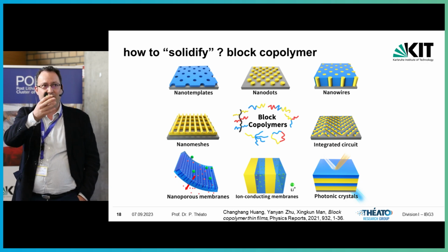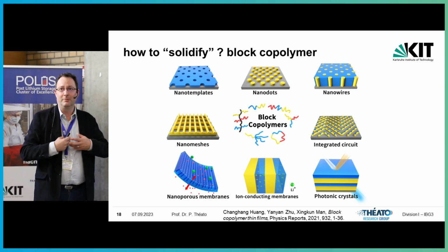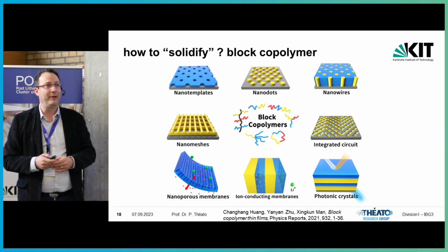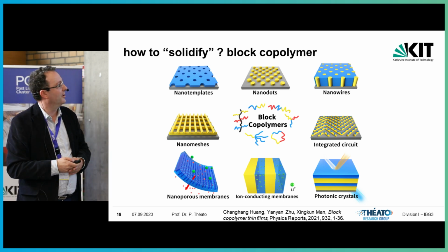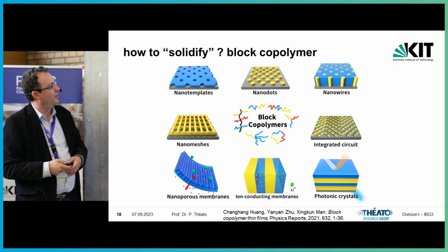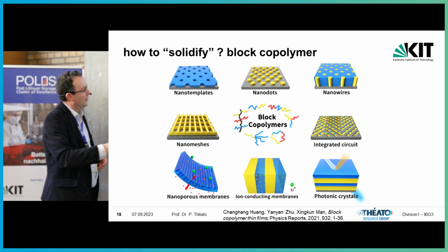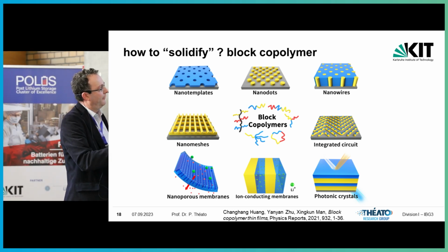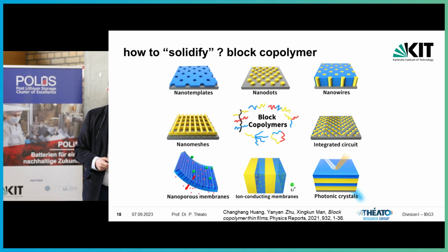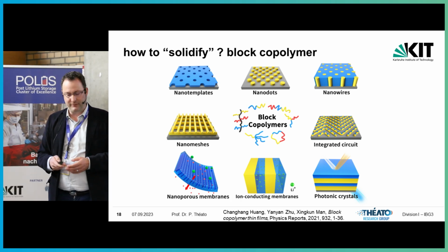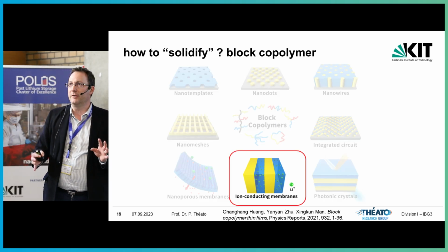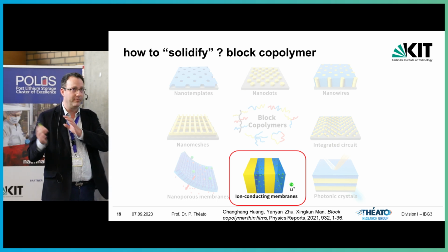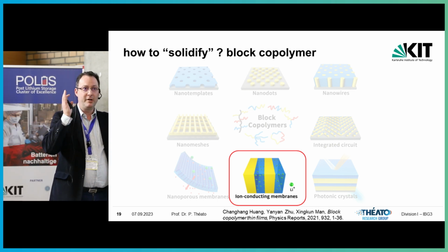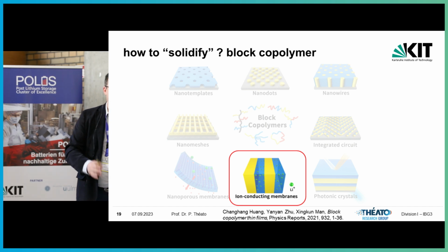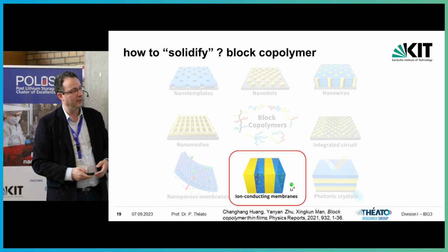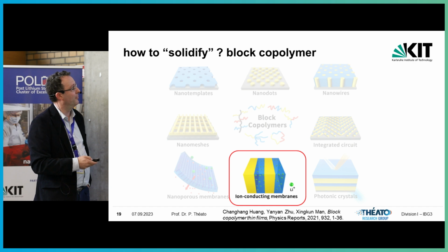We use copolymers, and I think Laurent already enlightened this one perfectly for me, so I don't need to use too much of the time. It's really about making structures of that nature here, isolating the ion conducting phase from a mechanically stabilizing phase. That's relatively simple to achieve. You do not need any photochemistry afterwards. You first make a bit of material, you can characterize it, you know exactly what you have, and then in a thermal processing you can get to stable membranes.